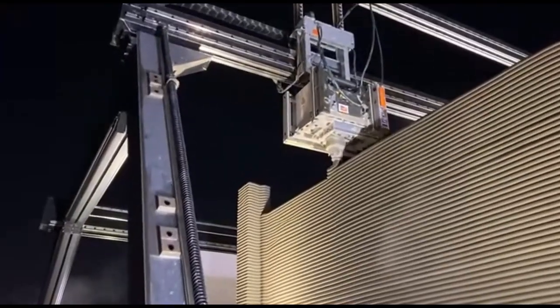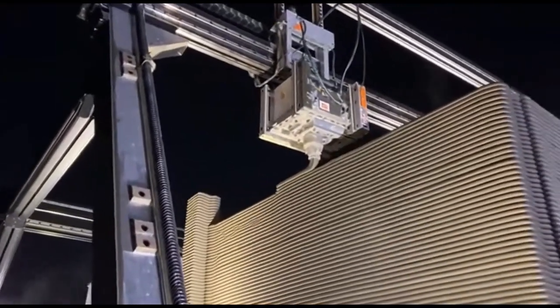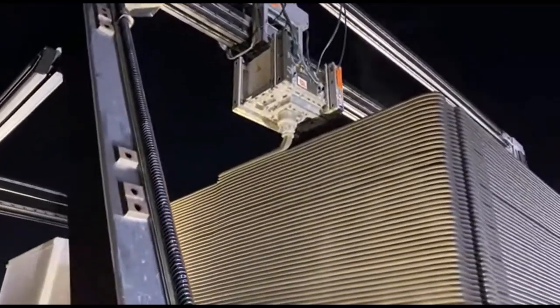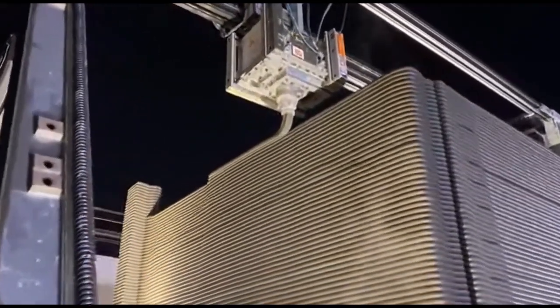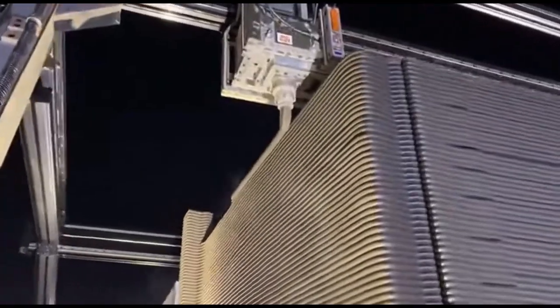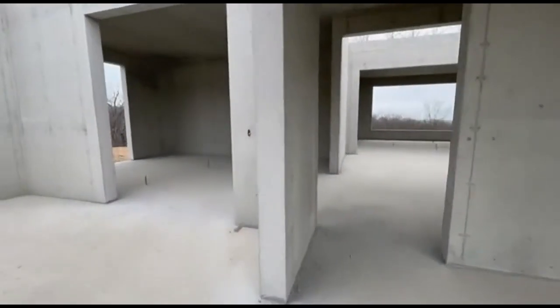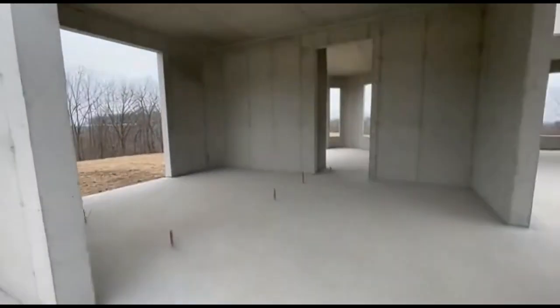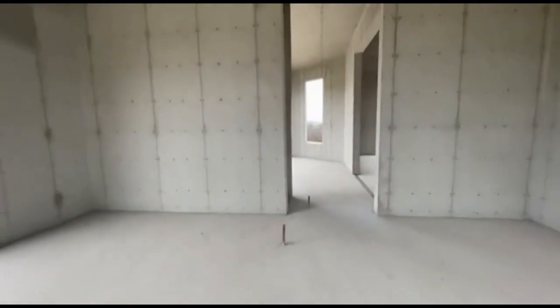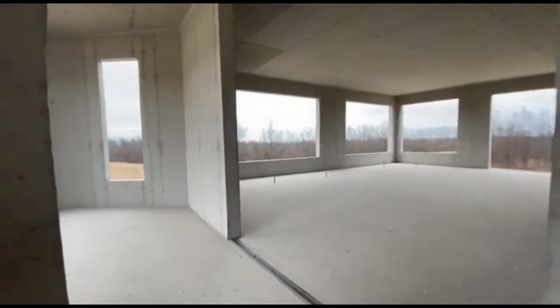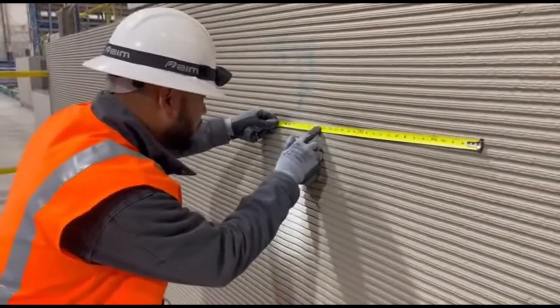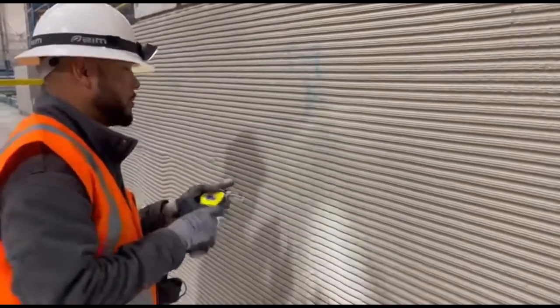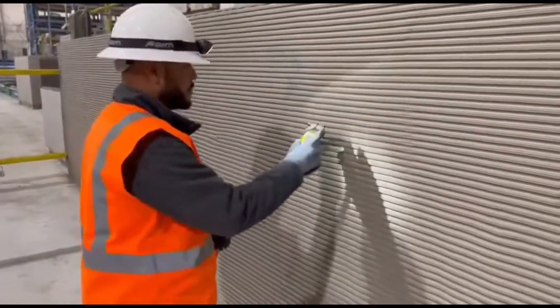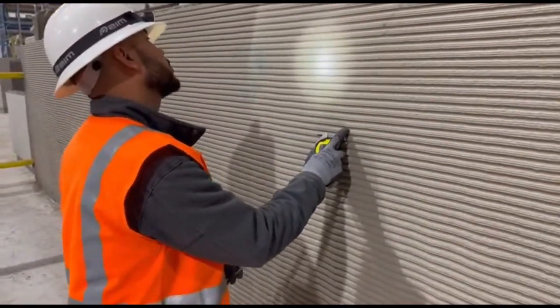And that heat accelerates the curing of the layer above it, creating a cascading reaction that strengthens the entire structure from the bottom up. By the time the printhead completes its circuit and returns to deposit the next layer, the previous one has reached a compressive strength of approximately 3 megapascals, enough to bear the weight of additional layers without deformation. Not yet strong enough to walk on, but strong enough to build upon.